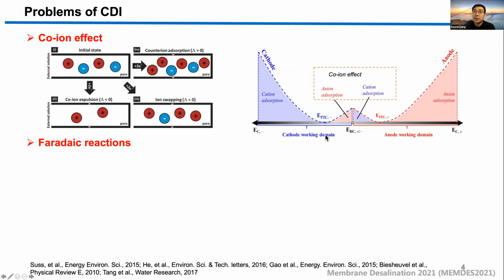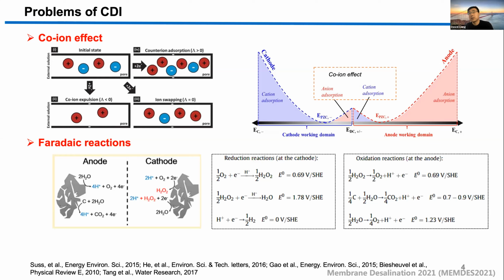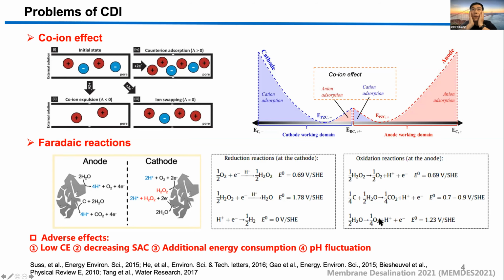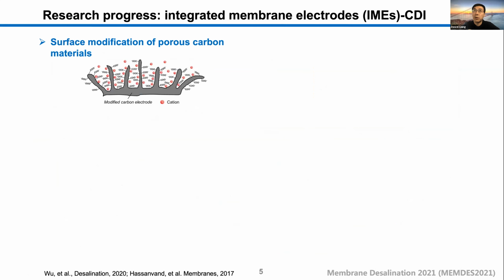Besides the co-ion effect, there are some Faradaic reactions occurring at the same time. On the cathode, reactions like oxygen reduction or even hydrogen evolution occur. On the anode, they will produce oxygen or even cause carbon corrosion. The Faradaic reactions and the co-ion effect will lower the charge efficiency and decrease the specific adsorption capacity, add additional energy consumption, and cause pH fluctuation in the system. So how to solve this problem? I think researchers have to find some way to solve it.